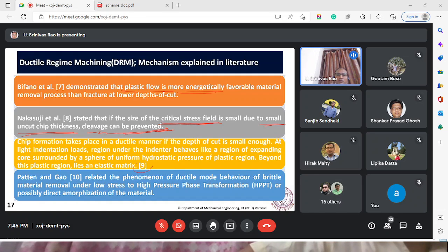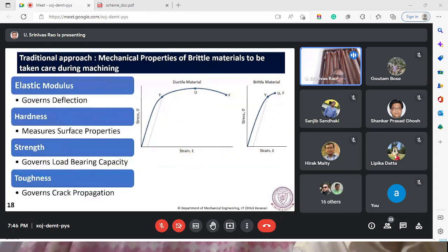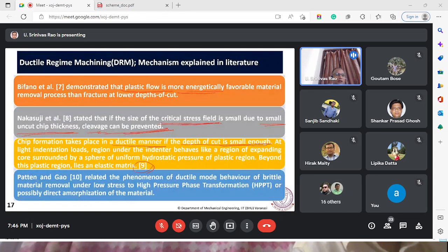Again, another literature reference also gives the same image. Chip formation takes place in ductile manner if the depth of cut is small enough. So these things actually can be checked through scratch tests, indentation tests. Okay. Like normally we do indentation for finding out hardness. So that actually gives an idea about up to what point the micro cracks are not generated. Okay.